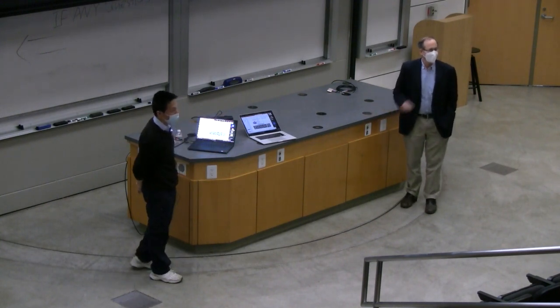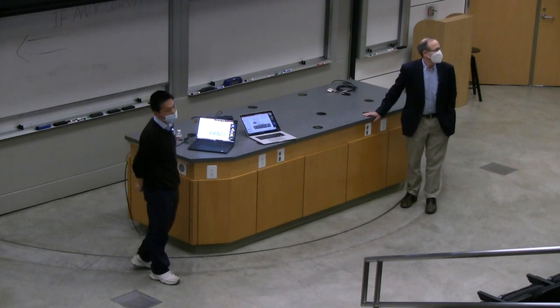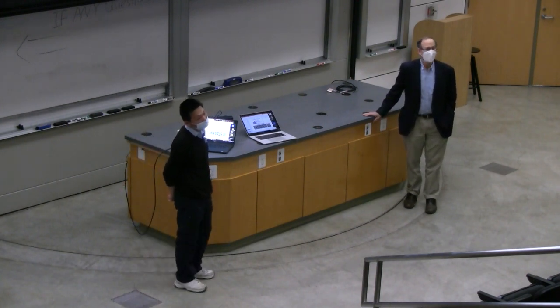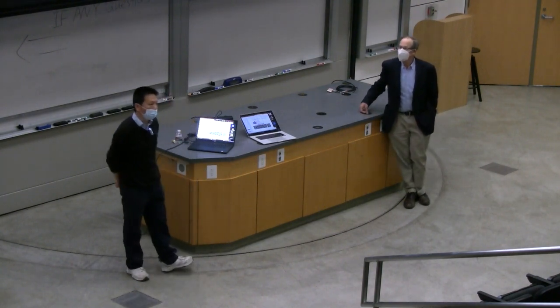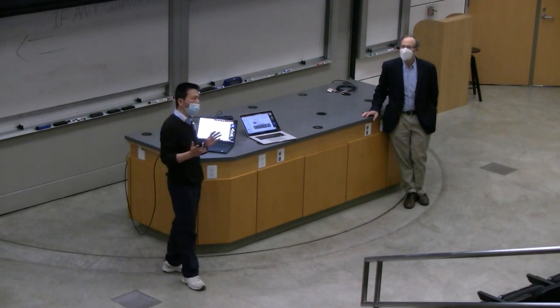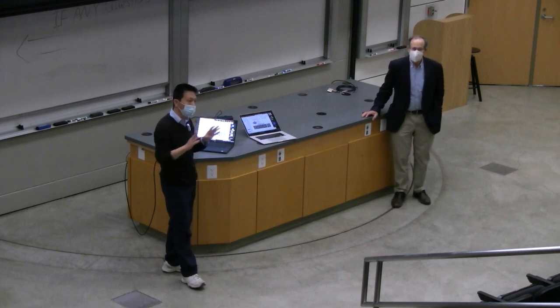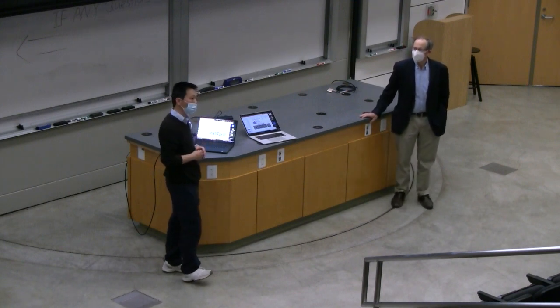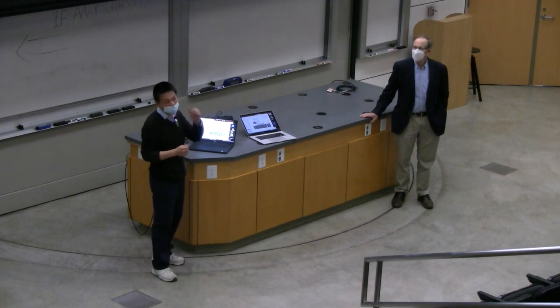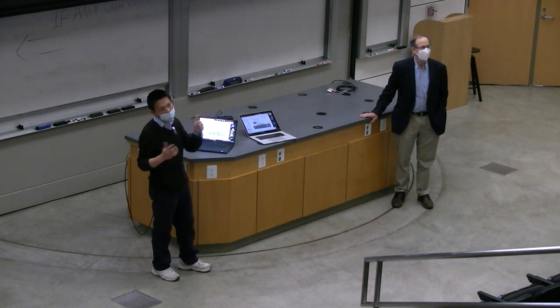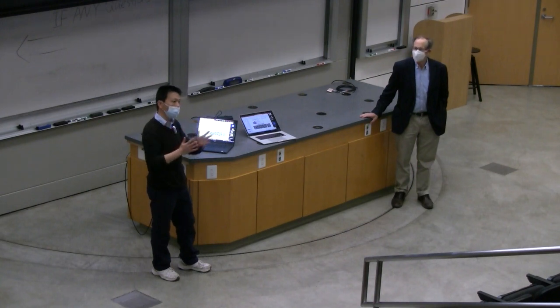Thank you. Last question? Yeah, thank you. You try to achieve the Mott insulator by changing the L versus... Do you think it's possible to do it through straining, actually stretching? Yeah, to strain and vary L, you can only have a few percent change. However, strain actually can modify the band structure quite dramatically. So if you apply strain, again, you can vary the competition between U and W if they are already fairly close. Then you can vary their competition and realize different states.